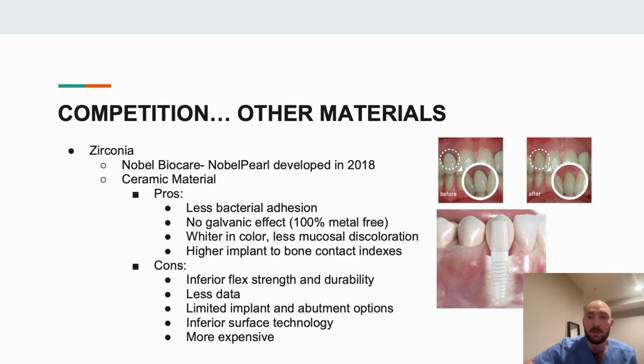Also, because it's metal-free, patients with zirconia implants will not experience the galvanic effect that can sometimes be experienced with titanium-based implants. Now, studies have also demonstrated that zirconia implants have greater implant-to-bone contact indexes than titanium implants, while also maintaining comparable osseointegration to titanium-based ones. And additionally, as can be seen in the picture to the right, zirconia implants like Nobel Pearl are whiter in color and demonstrate less mucosal discoloration than titanium, so they make a great option when aesthetics are being considered.